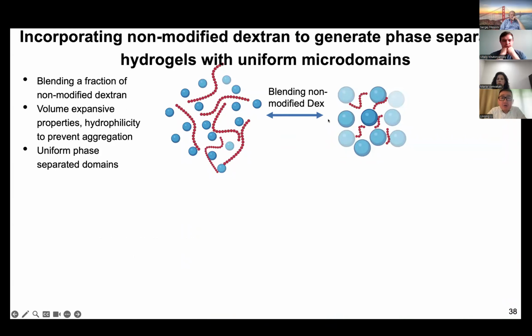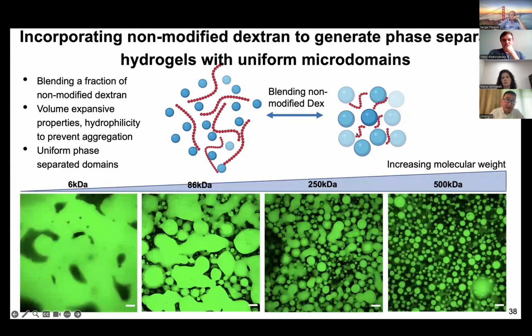If you think about why the domains emerge and become these large domains, essentially the phase separated regions merge together and collide, growing bigger. So if we have some secondary molecules that can separate these, then we're able to control their size a little bit. What we did here is add a small fraction, only 10%, of non-modified dextran, which is hydrophilic. What's shown here is the sugar chain. If you have a large molecule of non-modified dextran mixed together, you can be successful in separating these microdomains from merging together. With a small molecule, which has a smaller hydrodynamic radius, it doesn't achieve the goal, because the microdomains can still collide and merge with each other. So we tested this hypothesis.